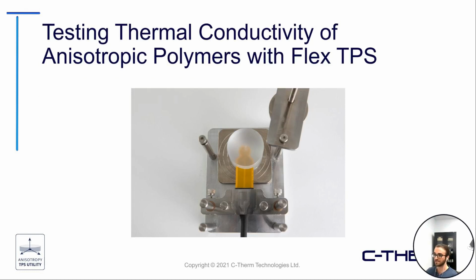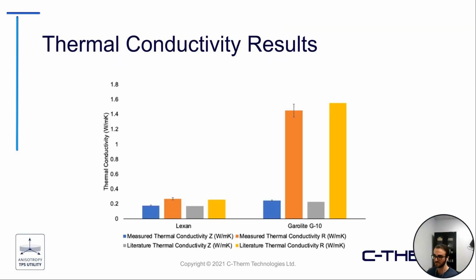So just a few examples and some data that was collected here. We can see some more simple examples with the TPS testing of some polymer materials. Thermal conductivity results here are noted compared to some literature or reference values. And you can see that in some cases, the difference between the in and through plane conductivities can be fairly minimal. The example on the left, while there is a significant difference, albeit not to the extreme levels as perhaps the example on the right, where you're getting very, very large differences in those in-plane and through-plane thermal properties.